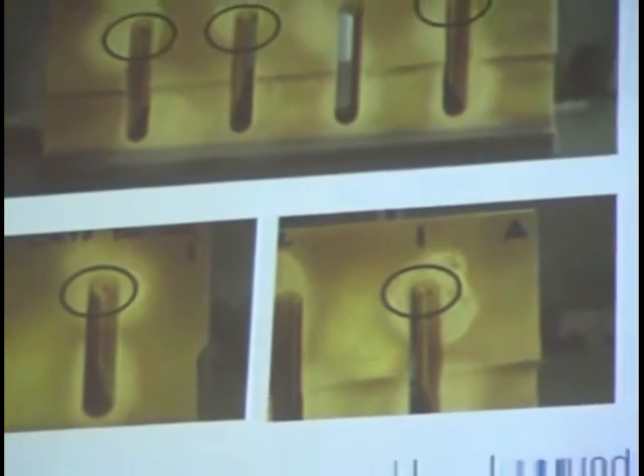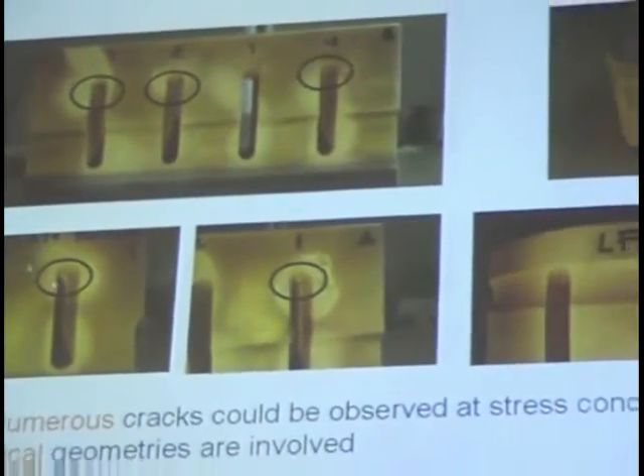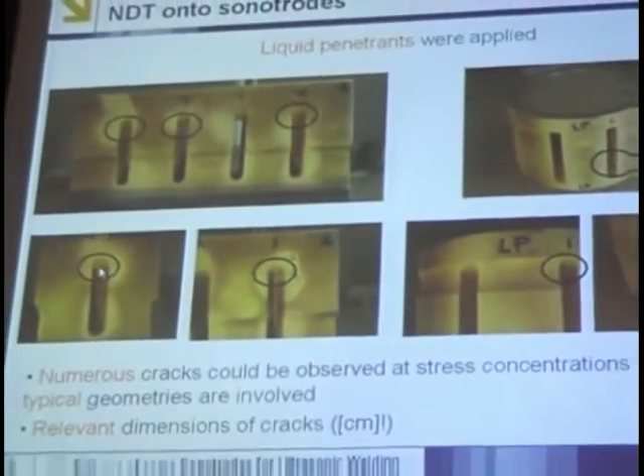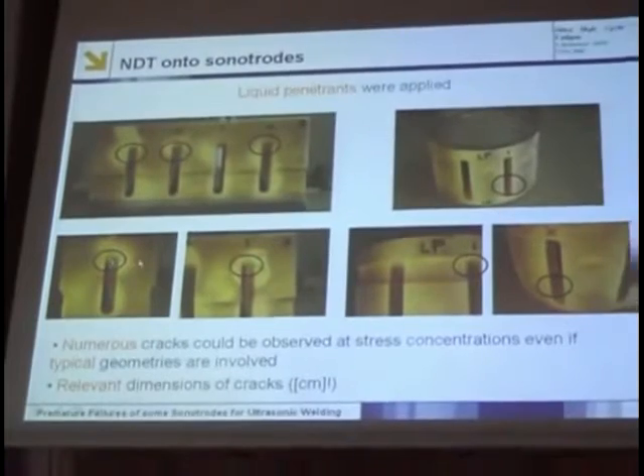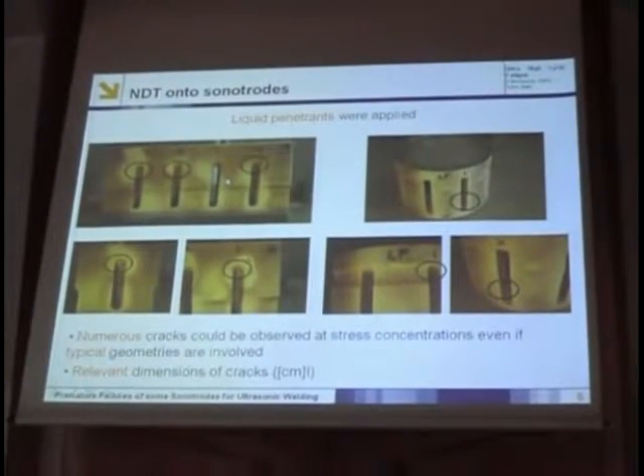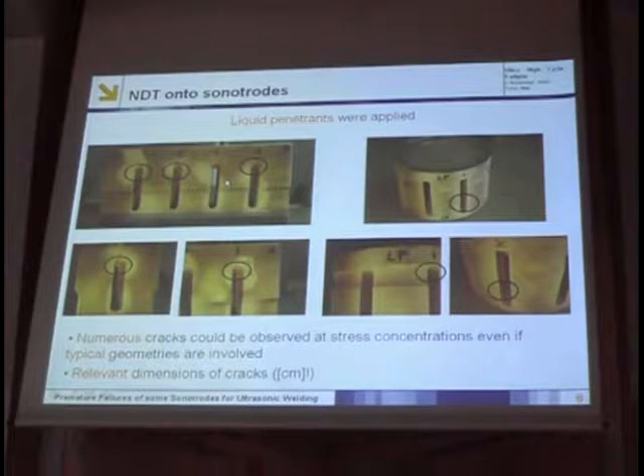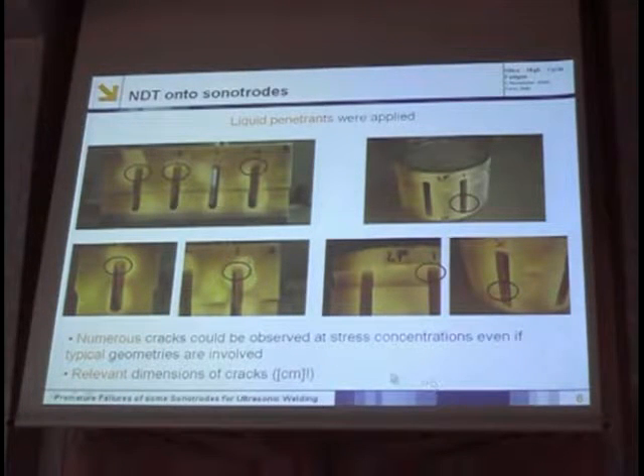But we didn't think that this stress concentration could be the reason for the failures, because, as I said, these were quite typical geometries for the sonotrodes, usually presenting no problems during 10 years of service. And the cracks found together with the liquid penetrants were also relevant in dimensions. The order of magnitude was centimeters inside the components.